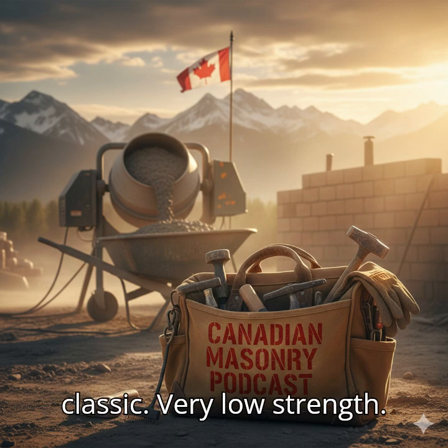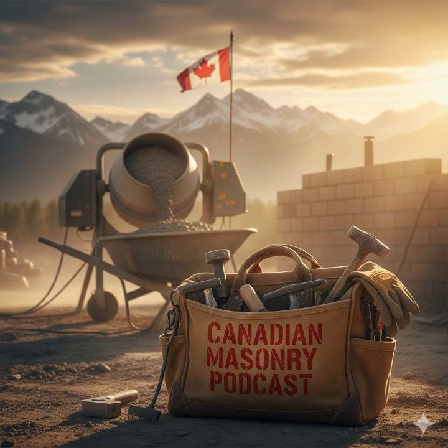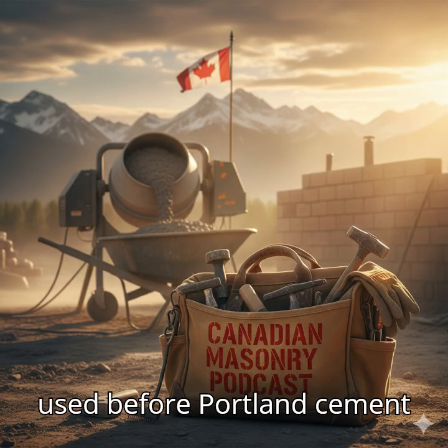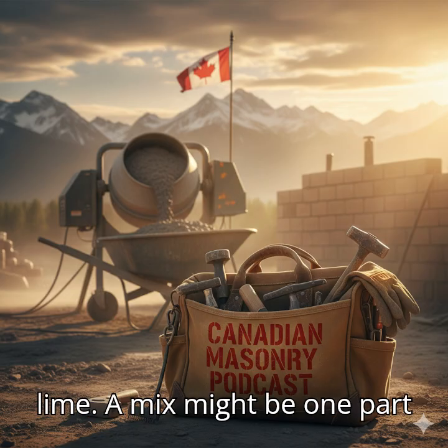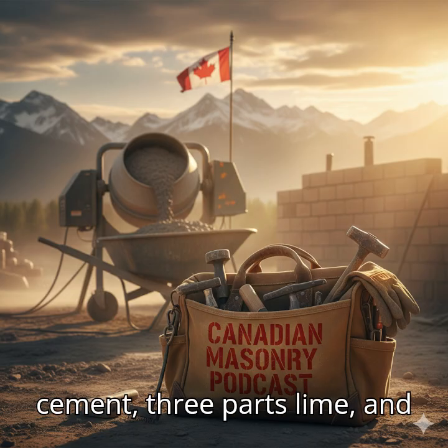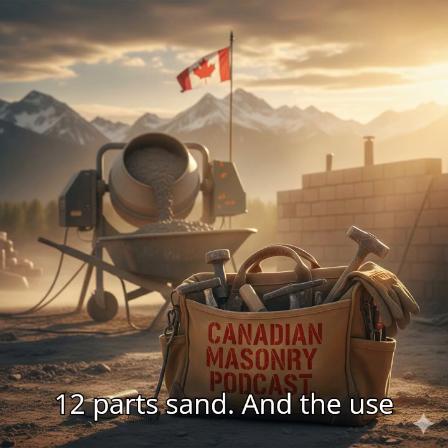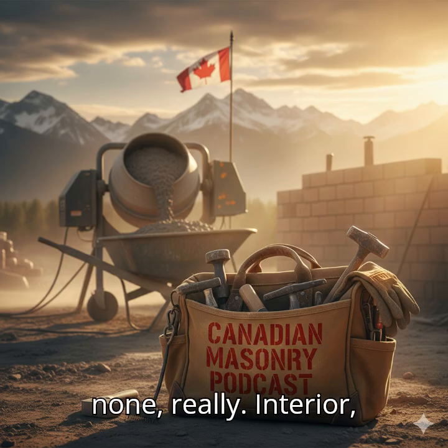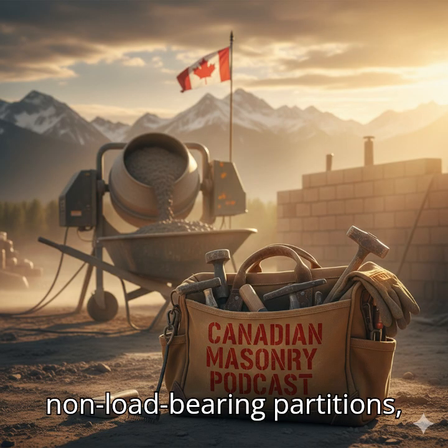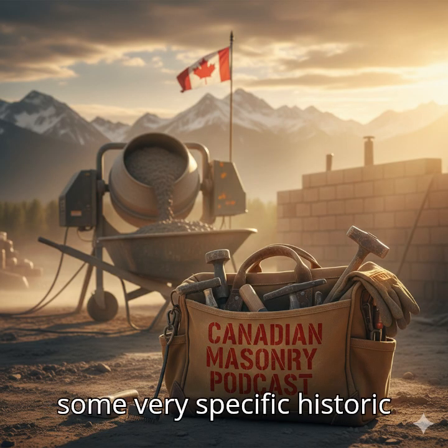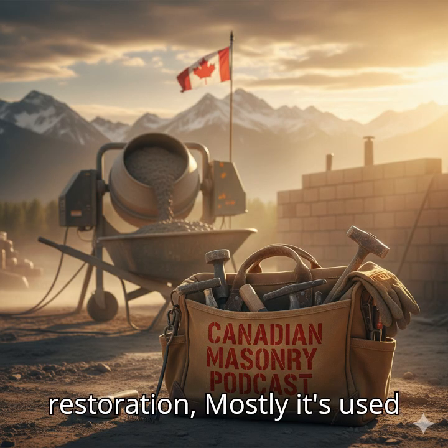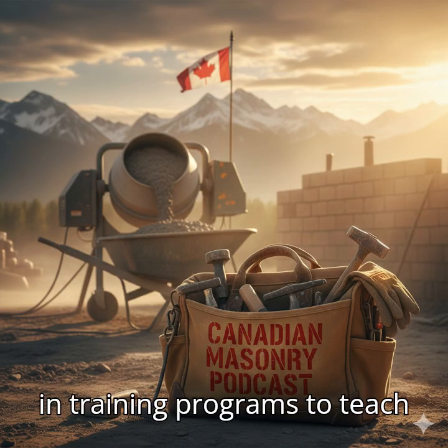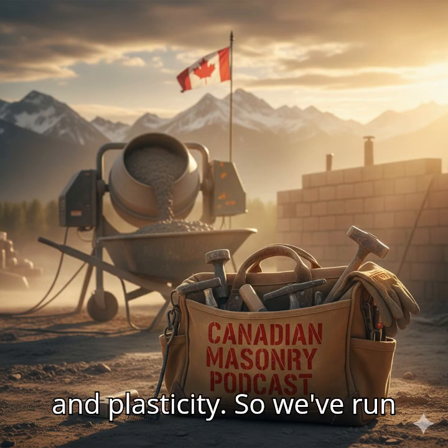Type K is for classic. Very low strength. This is basically what was used before Portland cement was common. It's almost all lime. A mix might be 1 part cement, 3 parts lime, and 12 parts sand. And the use case for that today? Almost none, really. Interior, non-load-bearing partitions, some very specific historic restoration. Mostly it's used in training programs to teach students about workability and plasticity.